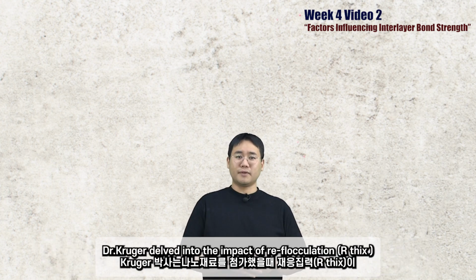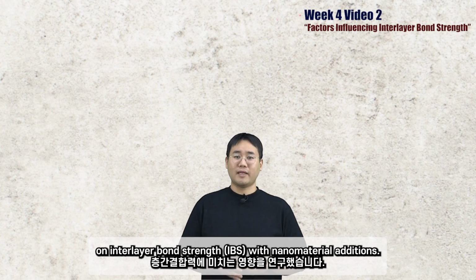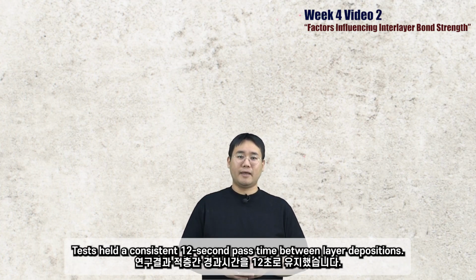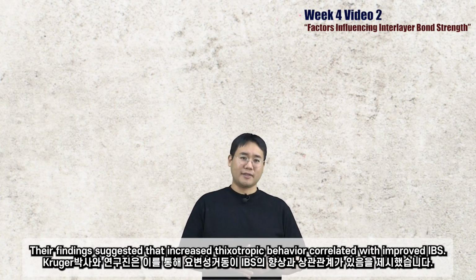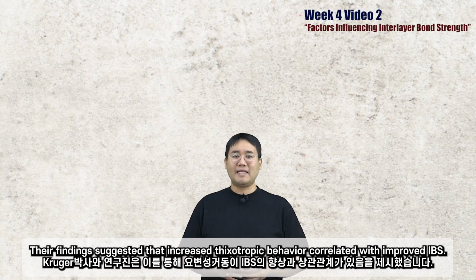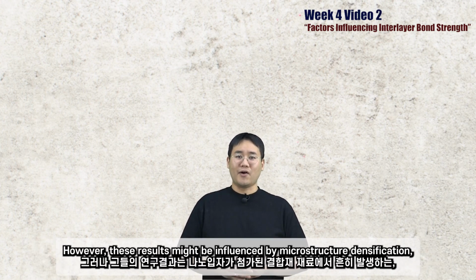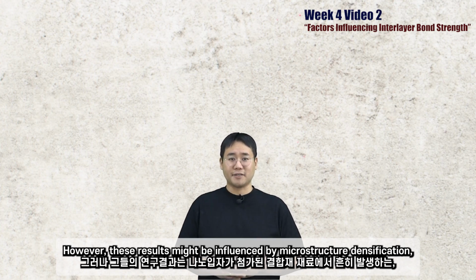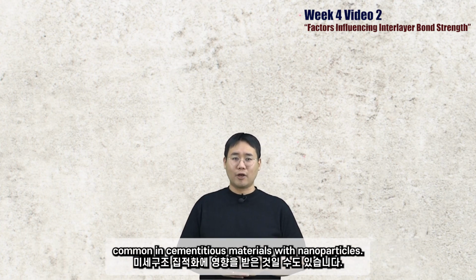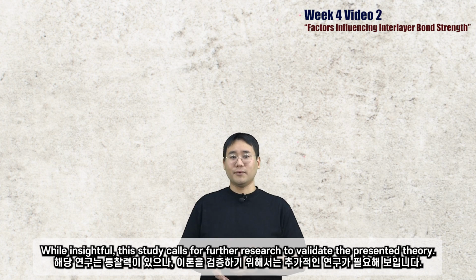Dr. Kruger delved into the impact of reflocculation on interlayer bonding strength with nanomaterial additions. Tests held a consistent 12-second pause time between layer deposition. Their findings suggested that increased thixotropic behavior correlated with improved IBS. However, these results might be influenced by microstructure densification, common in cementitious material with nanoparticles. While insightful, this study calls for further research to validate the presented theory.